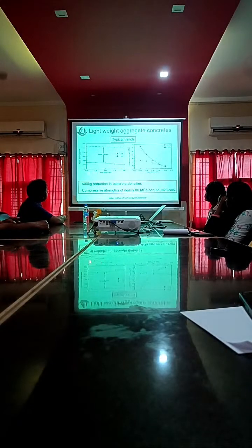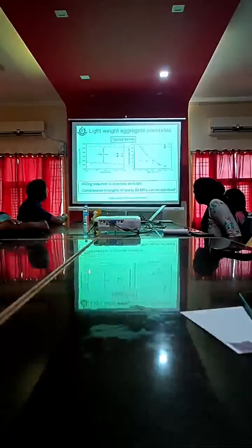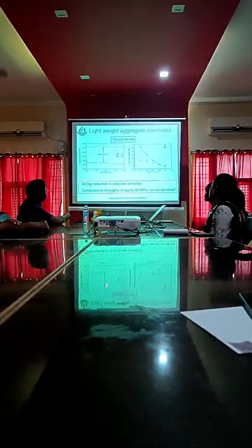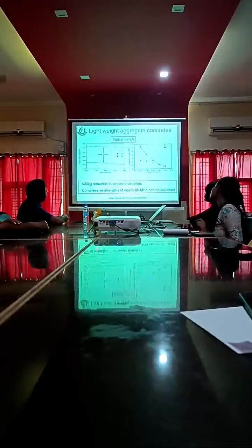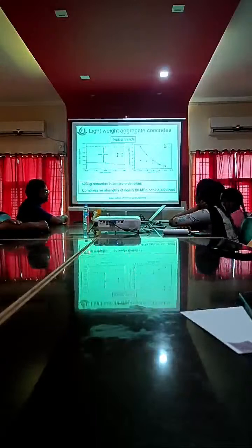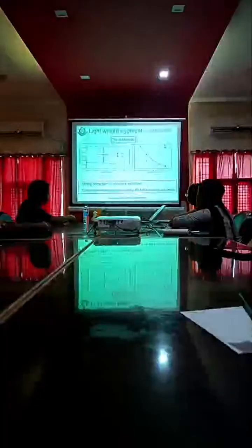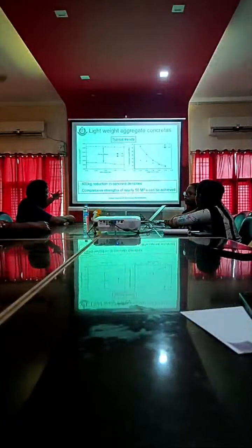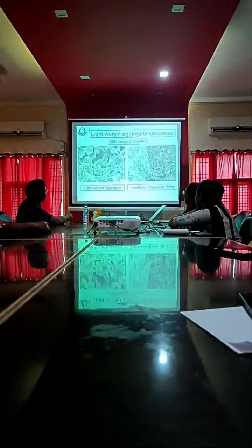And what is the difference? You see this water content ratio. A conventional concrete density is more than 2,400, and this is somewhere around 2,000. There is a density difference of nearly 400 kg reduction in the concrete density. And with the reduced density, we will be able to model the product. The lab will be able to achieve 80 megapascal concrete. It is lightweight, with a density of 2,000, and we will be able to achieve 80 megapascal concrete by modeling the product. So we have good products as well.